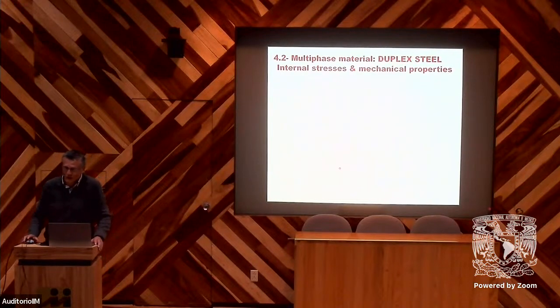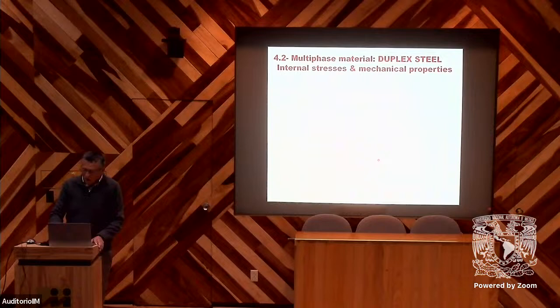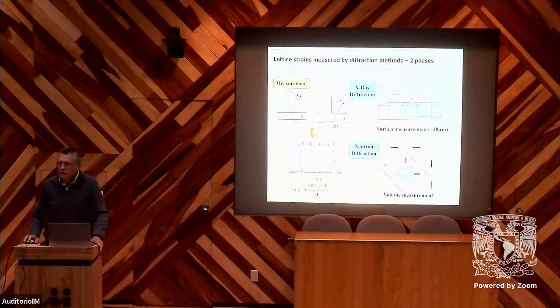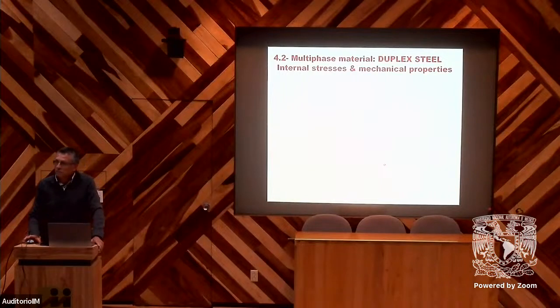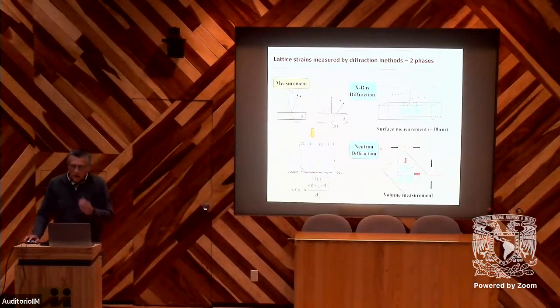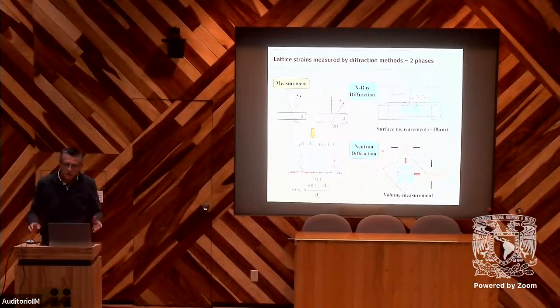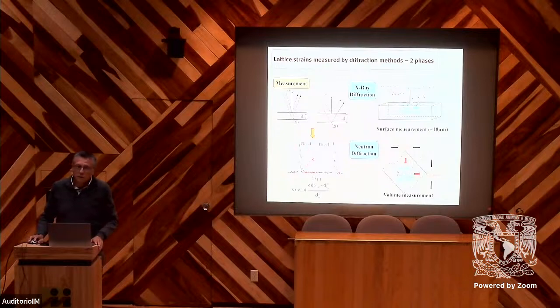This is the conclusion. So now let's see the second study, using neutron diffraction to study the behavior of duplex steel. The advantage of the diffraction method is that we can measure the stresses separately, by measuring the evolution of elastic strain, by measuring the displacement of the diffraction peaks in each phase separately. That means we can get the evolution of the stress in each phase.